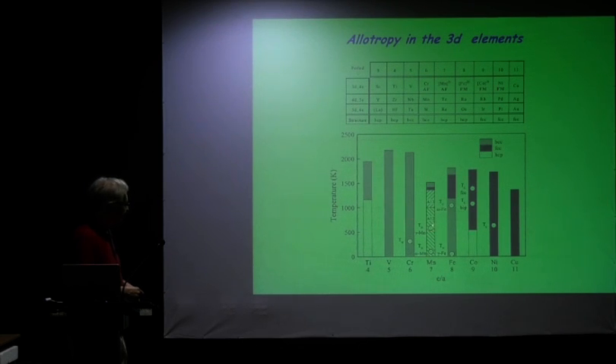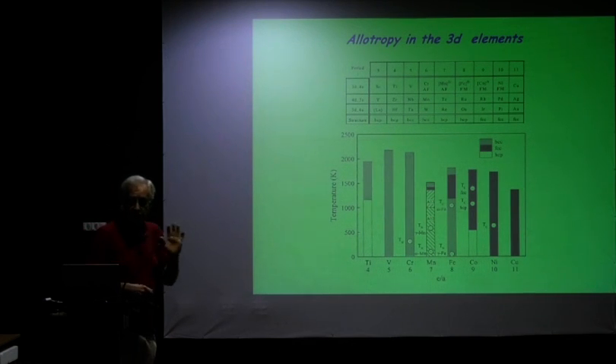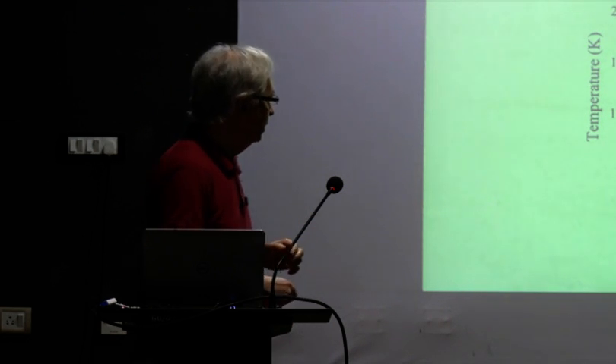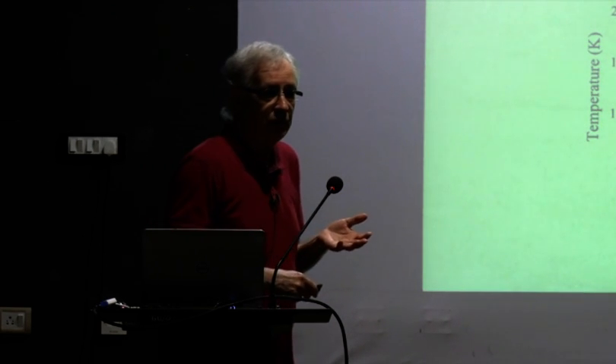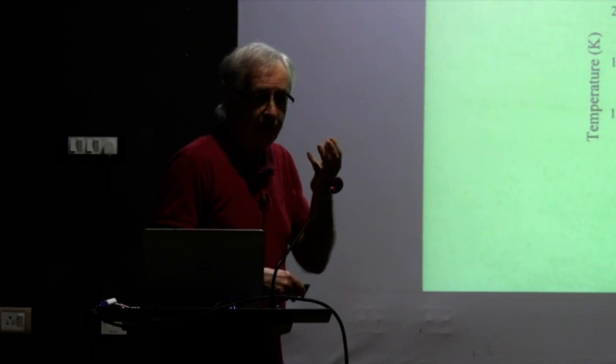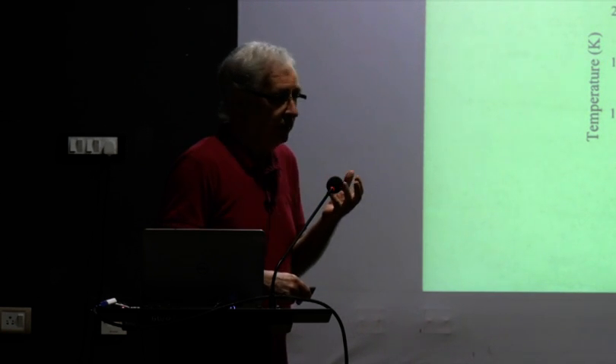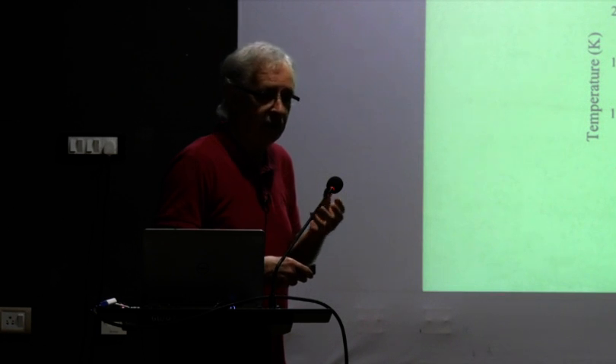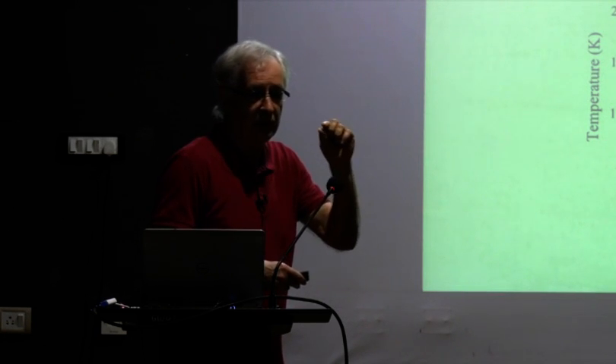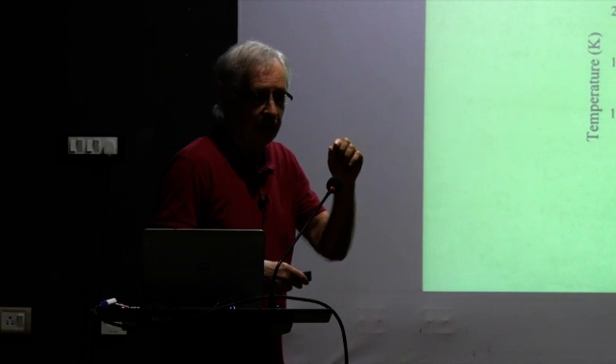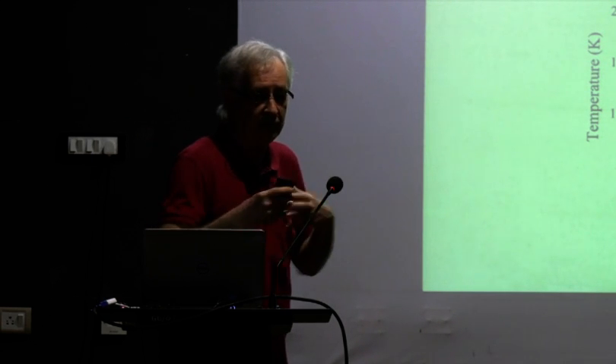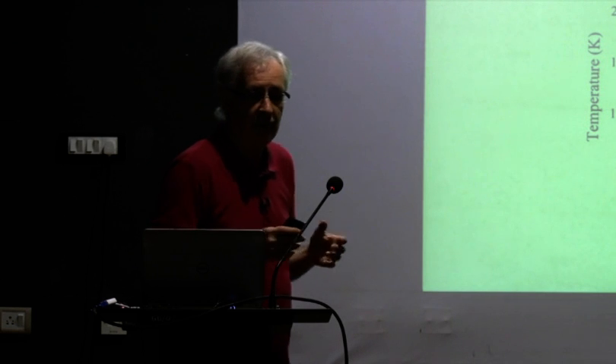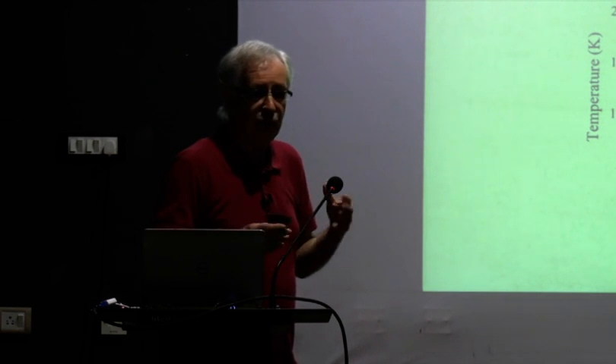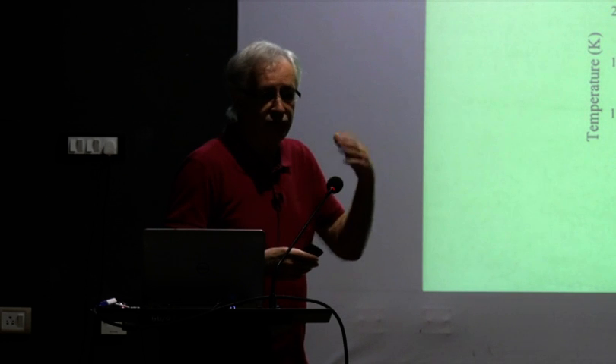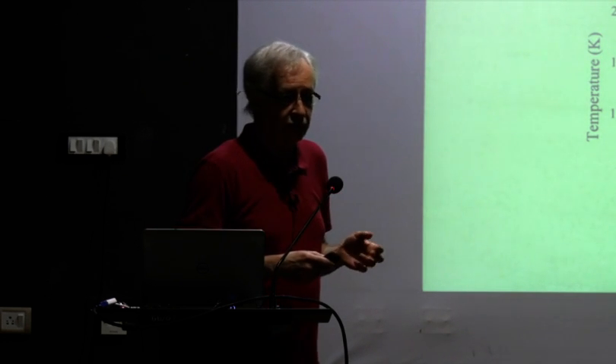When you come to manganese, you find 4 different structures. If you find 4 different structures, the thing that immediately comes to mind is that you have competing structures with very small energy differences, so that if you apply pressure, if you change the temperature, or if you induce strain or something like that, one structure may change into the other structure.